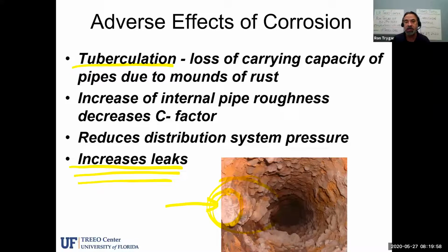So when this process keeps happening over and over again, the actual pipe wall thickness underneath that tubercle is getting thinner and thinner. So you can imagine that if you've got a very fragile pipe or a very old pipe where the wall thickness is getting thinner, as soon as any pressure increases or water hammer occurs, that's when we start to break the pipe open and have what we call a leak.